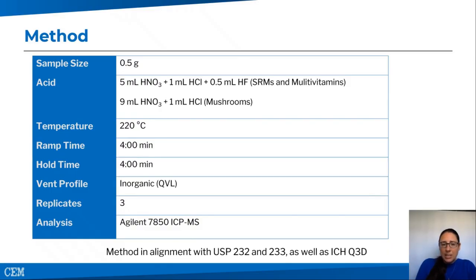All the samples were taken to the same temperature and then used for the same method forward, which required a 4-minute ramp time and a 4-minute hold time. So look at that, 8 minutes. Your digestion is completed in 8 minutes. Again, fastest available there. For all the data we're looking at, everything was run in triplicate and analyzed on an Agilent 7850 ICP-MS. And I do want to make note that we are following methodology that would be used in the dietary supplement arena across the globe. So that's important as well.